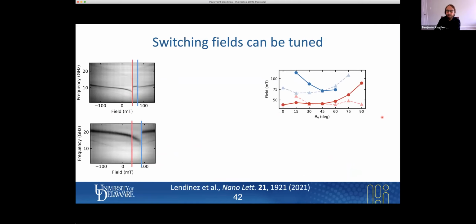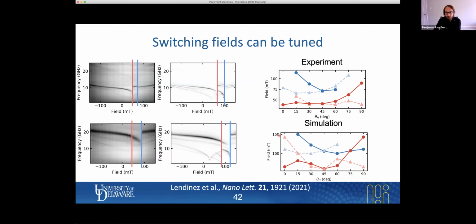I can also do this for the complementary lattice and analyze this, and I see it as these blue and red faint curves. We can also compare this to the simulations here. The simulations are shown on the bottom, and we get a good agreement between the experiment and the simulations. And we see from the simulations that it's eventually possible to reverse which sublattice switches first. So this is in this position or that position. We do not quite reach this regime in the experiment, but in principle, it should be possible to determine which lattice switches first.